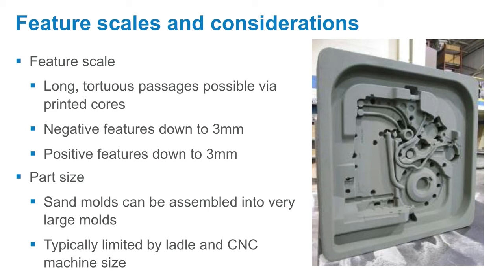And some foundries are set up to actually pour from multiple ladles. So Tooling and Equipment International, the foundry that we worked with for the hack rod and the swing arm, they can do about 2,400 pounds of aluminum in a single shot from two 1,200-pound ladles. So you're starting to work with some pretty big geometries, which is pretty exciting.